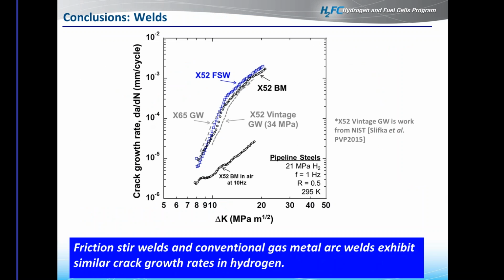So what happens when we take all this data of all the welds that we've tested and put them on one plot? Now, I've only used single curves for these because it got a little messy if we tried to plot them all. But what you see here is the X65 girth weld, which was a gas metal arc weld, the X52 friction stir weld, and then we also borrowed some data from our friends at NIST, and they'd done some testing on the X52 vintage girth weld, so it was a weld made many years ago. And what you see is the overall trend is that they're behaving quite similar, especially when we compare them to an X52 base metal. And so this is very encouraging because it basically opens the door for other welding techniques such as this friction stir welding, and we see that we're gaining confidence in the reliability of that weld.